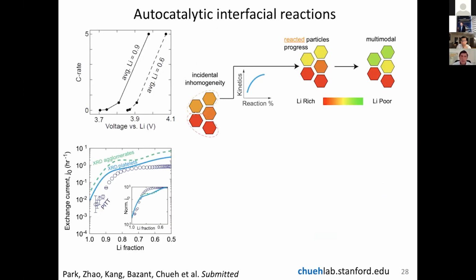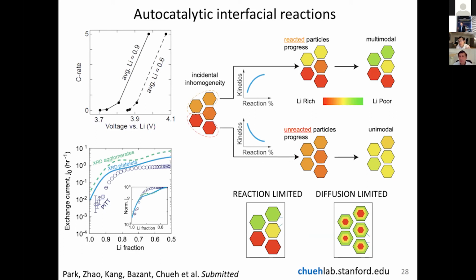So what is happening here? This is another really good example of the autocatalytic effect. Let me explain this briefly and we'll wrap up in just a minute. We have heterogeneity in the system to begin with. Every particle is a little bit different. So when we start to remove lithium, the reaction is getting faster and faster and faster. That means the particle that has slightly less lithium to begin with will accelerate more quickly.